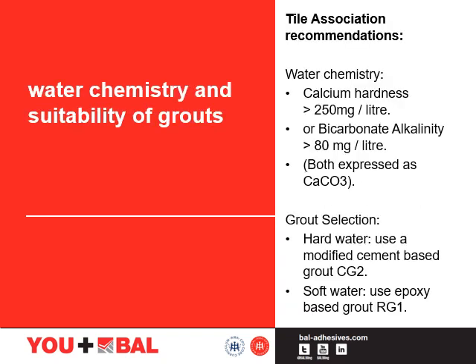The Tile Association recommendations are for a water calcium hardness of at least 250 mg per litre or bicarbonate alkalinity of at least 80 mg per litre. Both of these are expressed as CaCO3. Sulfate levels should typically not exceed 300 mg per litre. So this means for grout, if we've got hard water which is over 250 mg per litre, we need to use a modified cement-based grout which is a CG2 grout. For soft water, which is less than 250 mg per litre, it's advisable to use an epoxy-based grout or an RG grout.